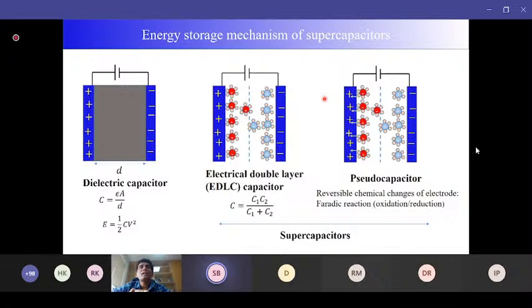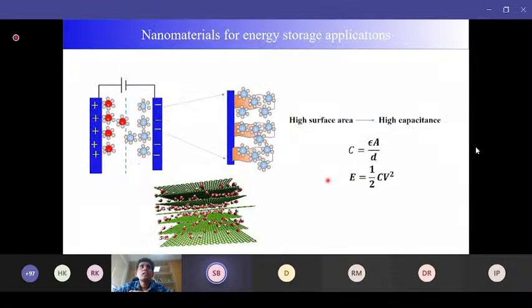The main advantage of the supercapacitor is that it can be charged at a very fast rate, but pseudo capacitors, because the reaction is happening at the surface, are much slower than the EDLC type. Depending on whether we want very fast charging, we should go for the electrical double layer type. But if the requirement is for higher energy density, we'll go for the pseudo capacitor. So now, we already know the mechanism by which energy storage happens.